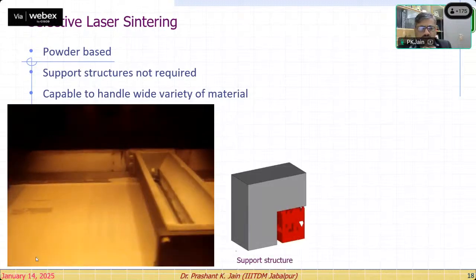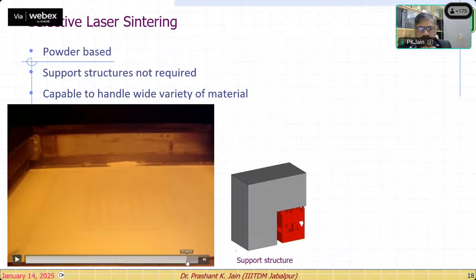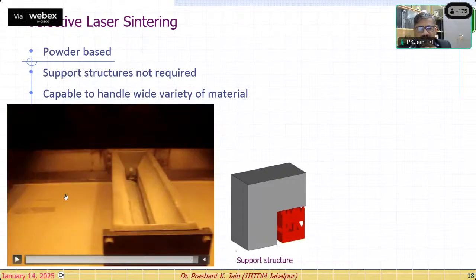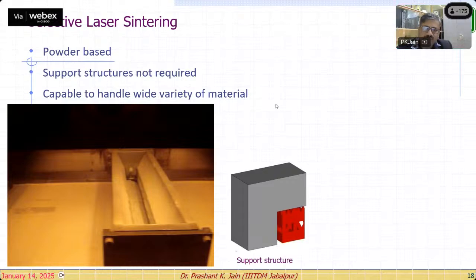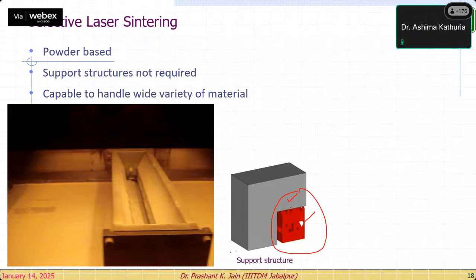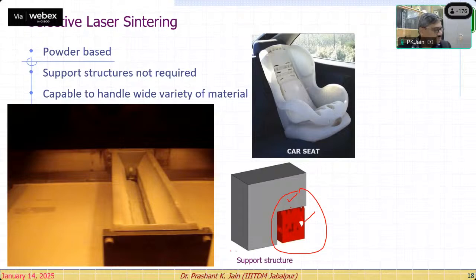See, this is the recoater spreading the new layer on the pre-built part. So the platform goes downward every time, and you see what happens in the FDM process. You require support for overhanging features, but in the SLS process you don't require the support, because the unsintered powder available on the part bed will provide the support to the overhanging features like this here. So this is the unsintered powder and this is the solidified powder, supported by this unsintered powder material. So you don't require any additional support structure in the case of the SLS process.